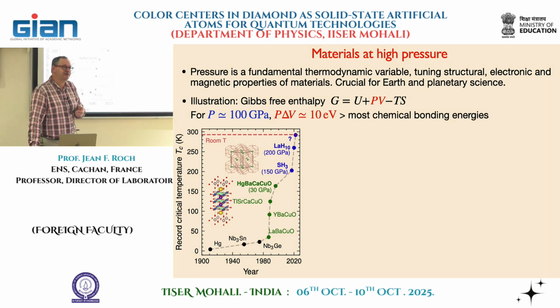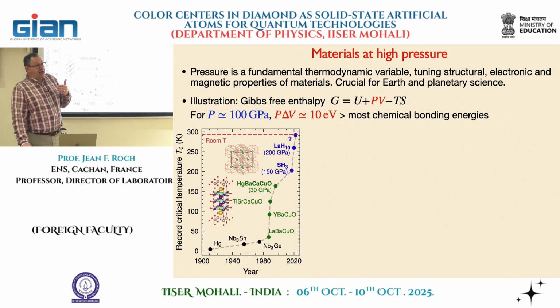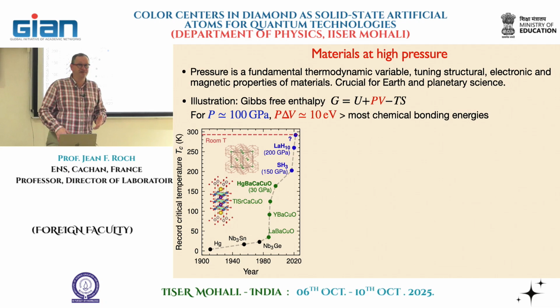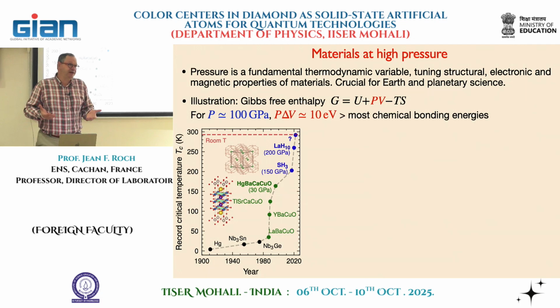It was predicted in the 30s by Wigner and Huntington in a pressure range, but up to now, no one really has been able, until maybe a colleague, Paul Loubeyre, with whom we collaborate, was able to achieve a metallic state of hydrogen. Perhaps what he has achieved is a metallic state of molecular hydrogen. So there's still a lot of debate, but the pressure you need to reach that is 400 gigapascal, higher than 4 million atmospheres. I will show you how this can be realized. And Neil Ashcroft predicted that if hydrogen is metallic, unfortunately at those crazy pressures, it would be a superconductor following BCS theory.